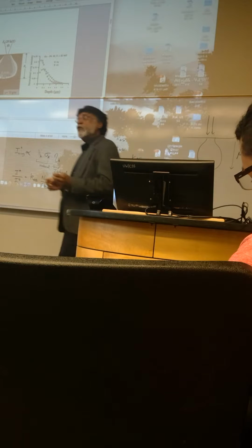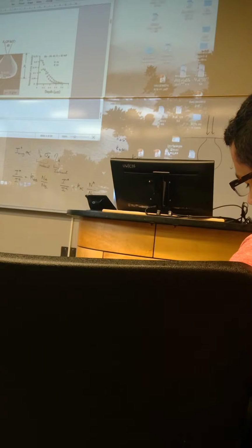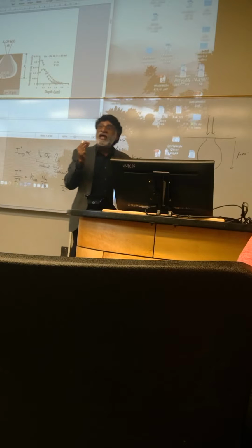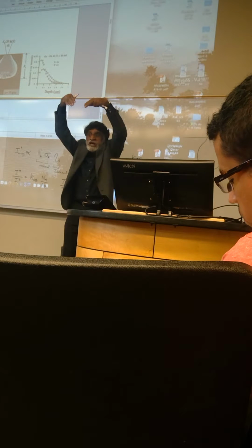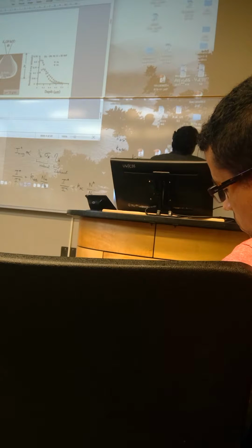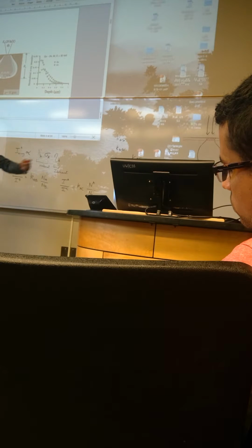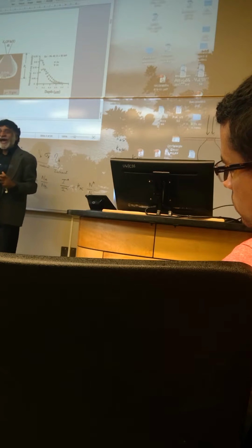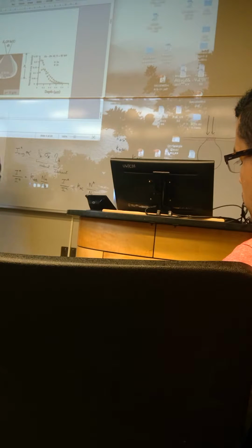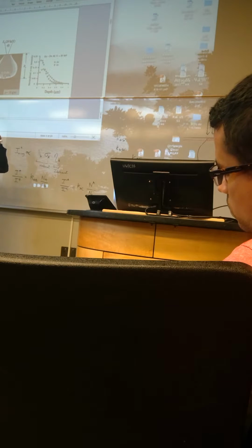Now, if you do a transmission electron microscope, you have to make a very thin foil so the electrons can go through. So you only have that thin section, and then you don't have to worry about this at all, because you don't have the absorption, the atomic number correction, or the fluorescence correction. It's too thin for it to create any of these problems.